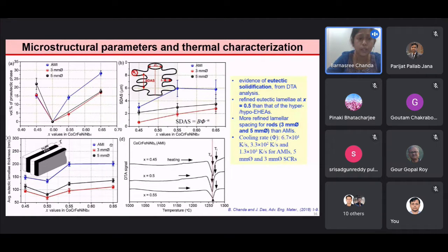In case of hypereutectic, we have seen that with the addition of niobium, the volume percent of the proeutectic phase, that is the Laves phase, has increased. The secondary dendritic arm spacing has been measured, and with the addition of niobium, the secondary dendritic arm spacing is also increasing. It is lowest in case of the suction casted rod, that is with higher